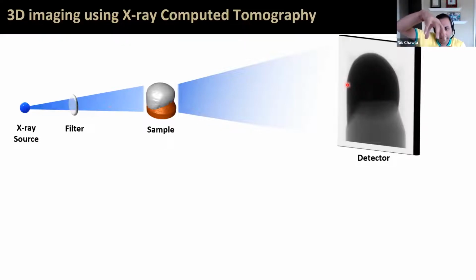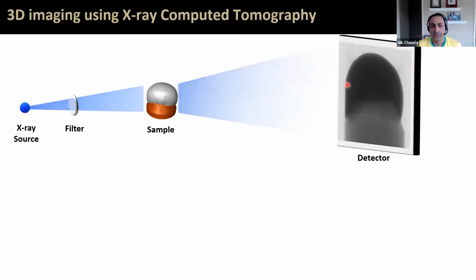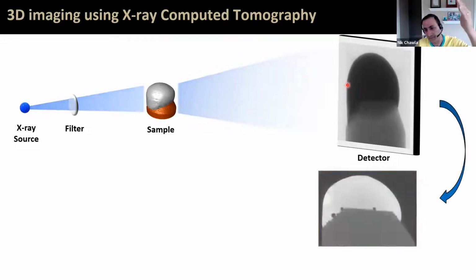And so when we rotate the sample, you can get many, many projections throughout the experiment. And that's what I've shown in this particular animation. So the sample can rotate 360 degrees. At each of those angular increments, which can be 1/8 of a degree or something like that, we get a projection of that sample. Now, these are two-dimensional projections at different angles.